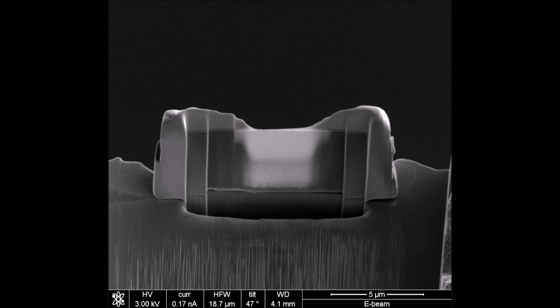In the scenario that I'm using here for the tutorial, of course, because it's a thin film on a substrate, then yes, we are trying to get the sample as thin as we can in the near surface region, because ultimately we would want to do high resolution imaging or atomic resolution imaging.